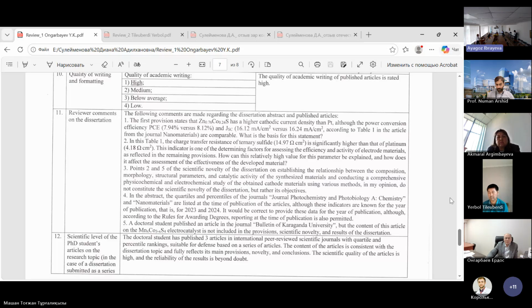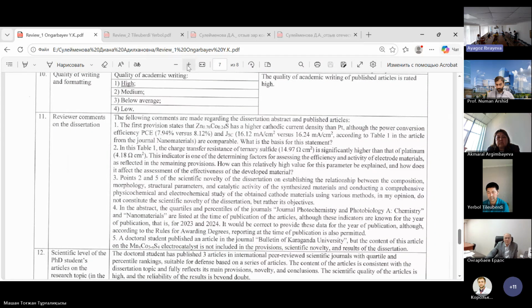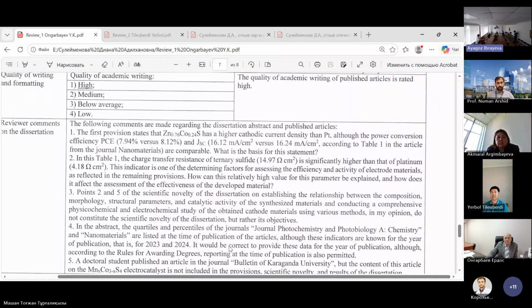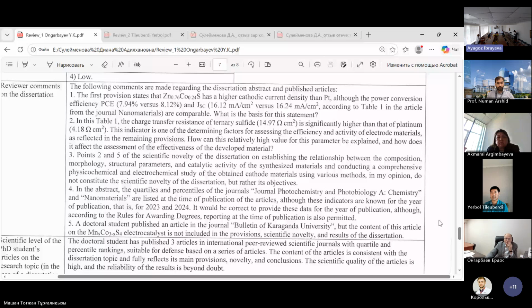Thank you for your questions and comments, Professor Yildiz. Regarding question number 1, the statement is based on cyclic voltammetry results, where zinc cobalt sulfide exhibits a higher cathodic peak current density than platinum, indicating superior electrocatalytic activity for the triiodide reduction reaction. In contrast, PCE and JSC reflect the overall device performance, which depends on multiple factors beyond the counter electrode, including photoanode performance, ion regeneration, charge transport, recombination dynamics, and electrolyte diffusion. Therefore, similar PCE and JSC values can still be observed despite the higher cathodic current density of zinc cobalt sulfide counter electrodes.